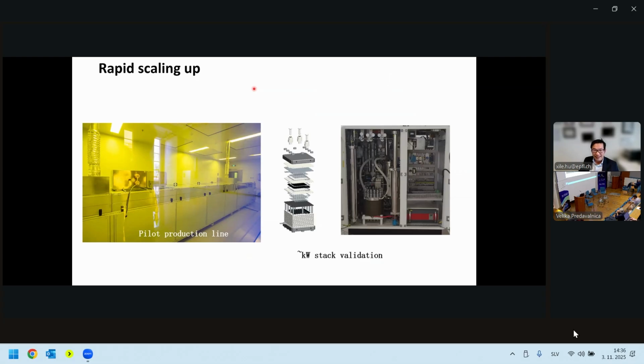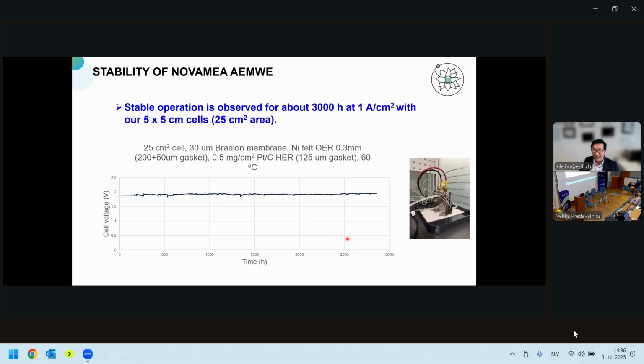Just to show you that in the company, in fact, the most important thing is to scale up things. So we are able to scale up. This is our pilot production line for membrane synthesis. We have also been testing in kilowatt stacks to validate these materials. And so to show you some data, for instance, we have results to show that if we take even a really thin membrane, 30 micrometer, and we test them in 5 cm² cells, we test under our lab, we can do 3,000 hours, okay, still going, at 1 amp per square centimeter, to show that the property of this membrane is quite good.